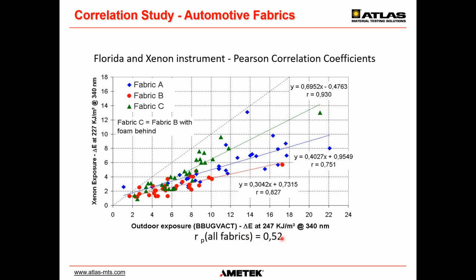And overall, the Pearson correlation coefficient is 0.52, which is not necessarily a good correlation. However, if you look at the data sets for the different materials colored in different colors, you see that the different materials are actually behaving a little bit more linearly than the overall setup. So material A and B, different chemistry maybe, so it might make sense to do a separate correlation between the two of those. And material B and C, again the same fabric, but C with a foam backing.